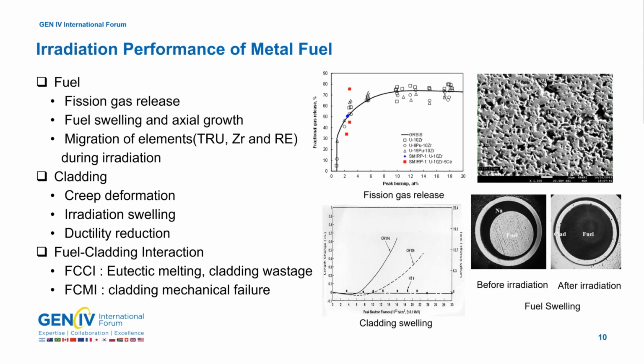So this shows the typical irradiation performance of metallic fuels. And in the fuel, there is fission occurring. So fission gas generated is released to the fuel slug. And as you can see here, after a burn-up of about 6, almost 70 percent or more fission gas is released. Fission gas is released to the gas plenum, and the metal fuel swelling and axial growth occurs.